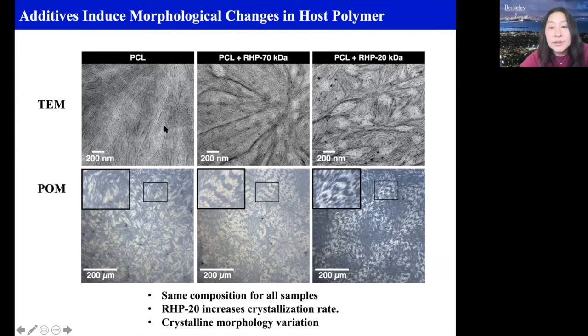And you can see this is a TEM. This is a polarized optical microscope. So we just add a little bit of additive into the system. You can see that in this case, the lamellar sheets are fairly straight. They are very flat. But as we're adding additives, the additive has to be excluded from the crystalline domain and that induces the bending of the lamellae. And naturally that is going to trickle down to how the polymer chain is going to get packed. So indeed,